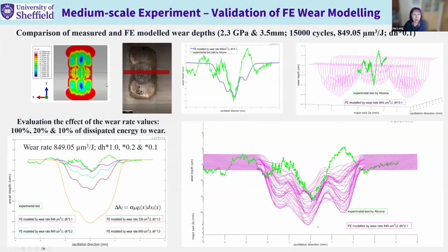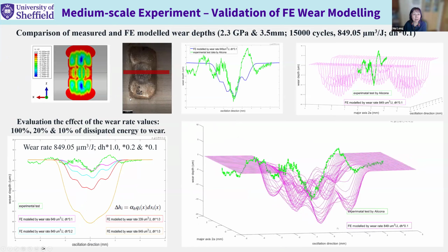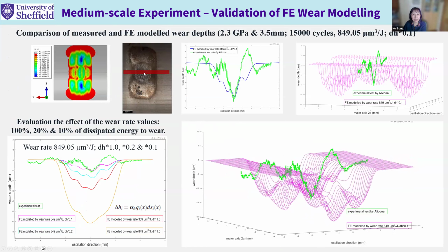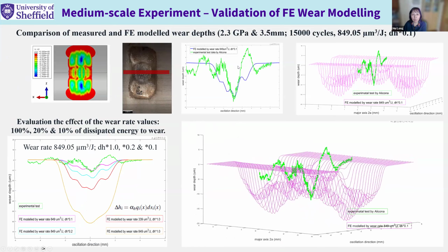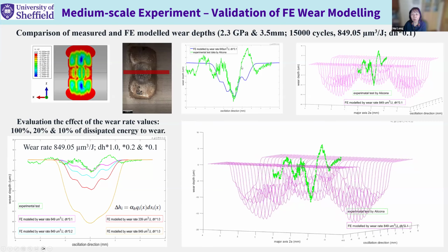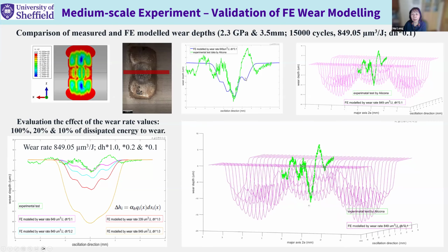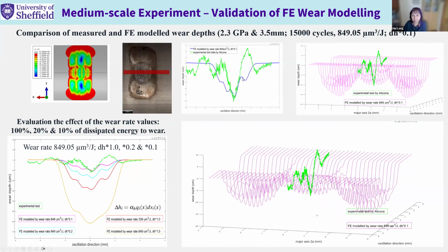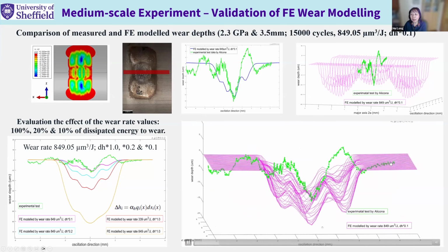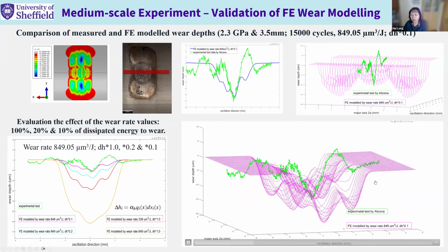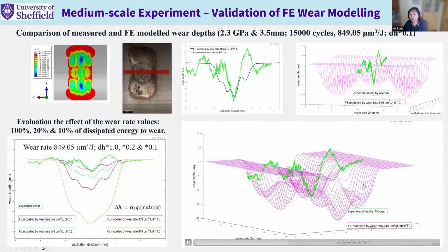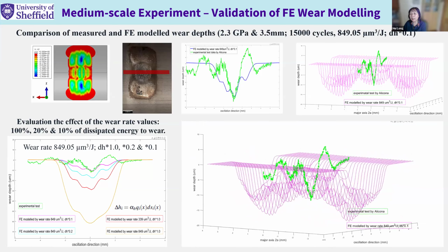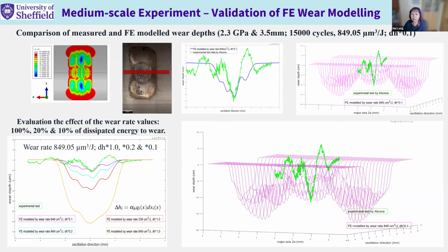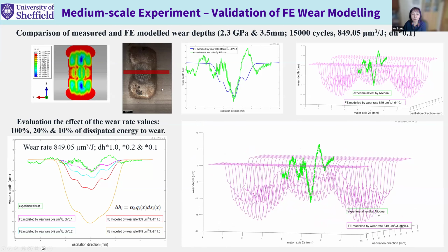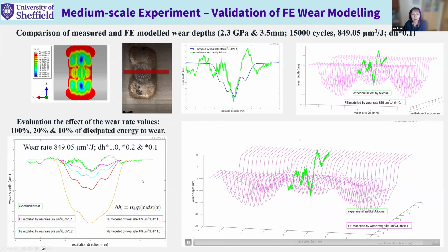This shows the FEA modeled wear pattern, this shows the measured wear pattern, and this is a comparison of the measured and FEA modeled. Green is measured and blue is FEA modeled. As you can see, the FEA, in purple color, can show the 3D dimension of the wear pattern, which is quite difficult through measurements. That means we have to measure all the sections of the wear specimen in order to obtain them.